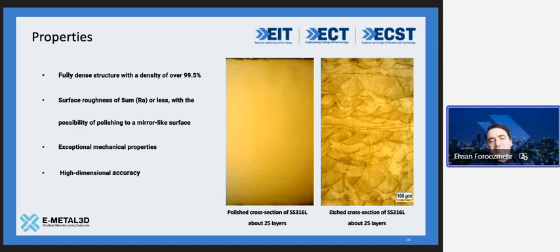The surface is not fully shiny, as some of the examples in the movie also showed, because we are talking about powder, and the powder is rough at the surface. So what happens is there will be some roughness at the surface. The roughness changes from 5-6 Ra to sometimes larger, sometimes less. We had experiences of like 2 micron and sometimes 8 and 9, depending again on many parameters, including the powder size and also other aspects of the parameters.